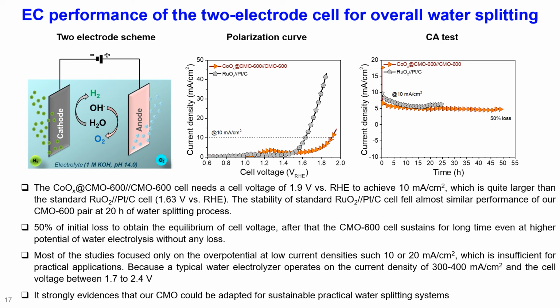Finally, the performance of the two electrode cell for overall water splitting. The two electrode scheme is shown here. Here the CoOx@CMO 600 electrode is used as anode and the CMO 600 electrode is used as cathode. This cell needs a cell voltage of 1.9 volt to achieve 10 milliampere per centimeter square current density, which is quite larger than the standard ruthenium and platinum-carbon cell, which requires only 1.63 volt cell voltage.